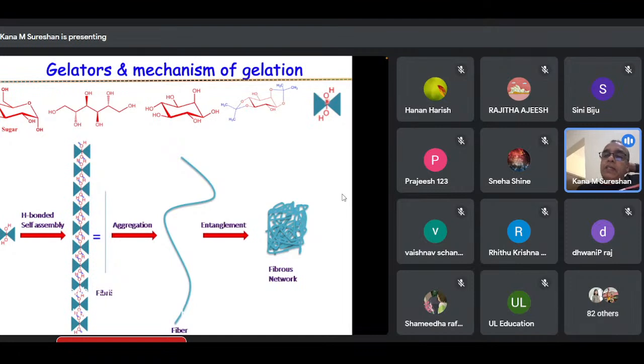So, this is a schematic for that. You can see this dumbbell kind of arrangement I have shown. This is hydrophobic, and the middle OH is hydrophilic. And when you put this in a non-polar solvent, what happens is this will start self-assembling. That means it will undergo some kind of aggregation through this attractive hydrogen bonding interaction between monomers. And that will form a supramolecular chain-like molecule that you can call a fibril. And several such small fibrils undergo lateral aggregation and make a much thicker fiber. And that fiber gets entangled and forms a 3D network. And there are spaces in between.